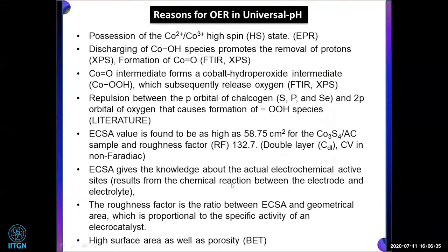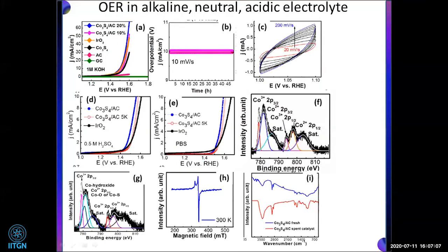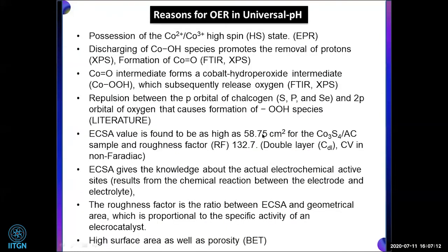One more thing is the electrochemically active surface area, which gives us knowledge about the actual electrochemical sites. This is different from the BET surface area. With BET we mainly get the complete surface area, but with ECSA we get only the catalytically active surface, right? When we calculate that surface area from the capacitance measurement in the non-Faradaic region, we found it is very high, around 58.75 centimeters squared.